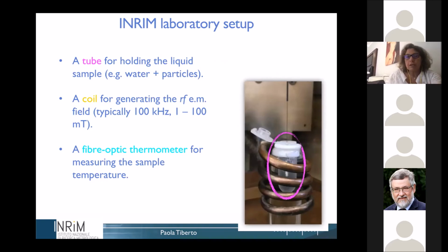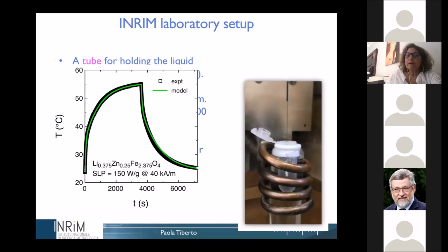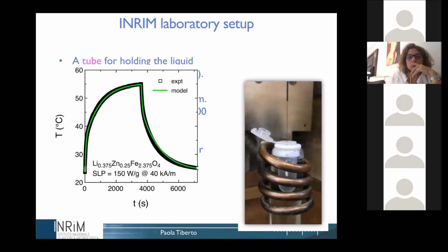This is very quickly the hyperthermia setup. We measure, as you see, in liquid. We have a tube where we hold the liquid, a big coil to generate the radio frequency electromagnetic field, and a thermometer for measuring the sample temperature. Here is a typical result of our temperature. We have a temperature rise and we measure it for about 1 hour. Then we record also the point where we switch off the field, and we record the temperature decay towards room temperature.